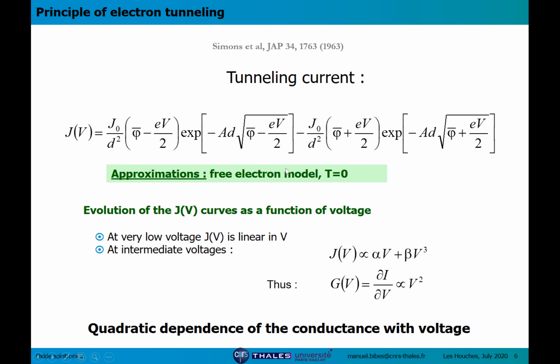So in the 60s, there were several works, including this work by Simmons, who simplified this equation and arrived at this expression. And here you see the tunneling current density as a function of the bias voltage. So the bias voltage is applied between the two metals and provides energy for the electrons to tunnel from one metal to the other metal across the barrier. And you see that this modified equation or simplified equation includes the different terms that we've seen before. So now the thickness of the barrier is now called D. I apologize for this. And phi is still the barrier height, okay?